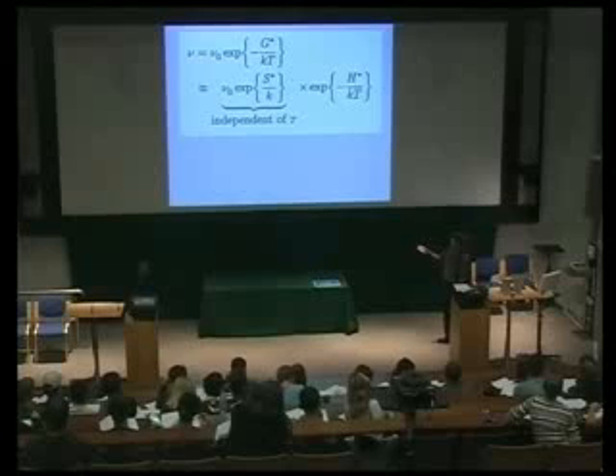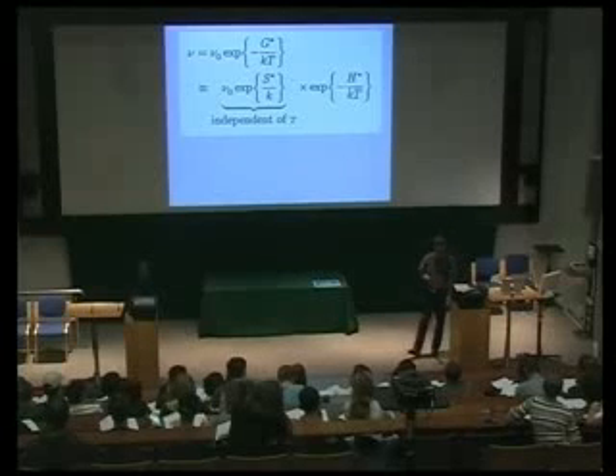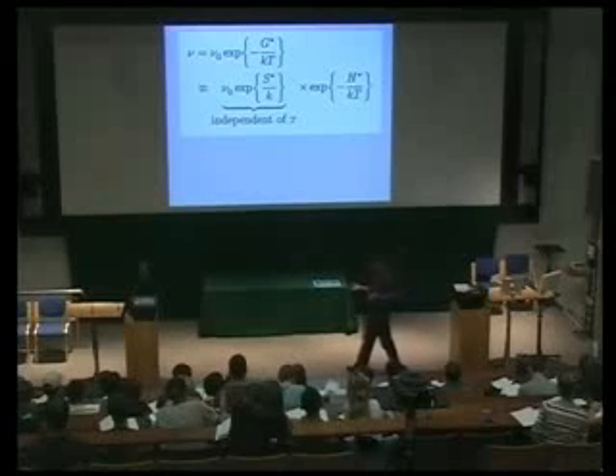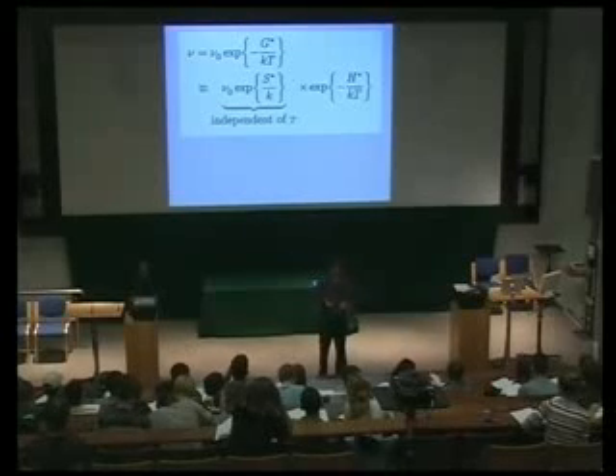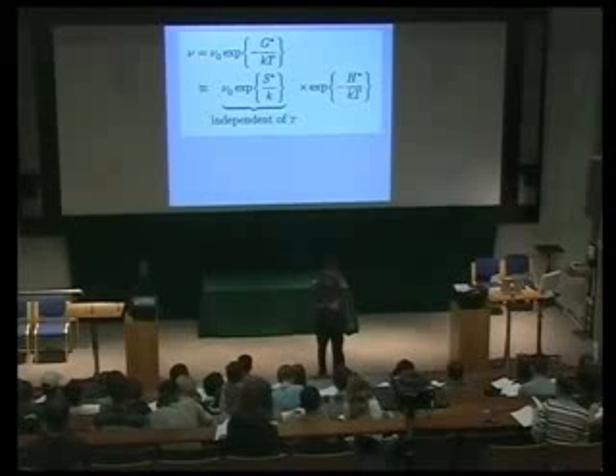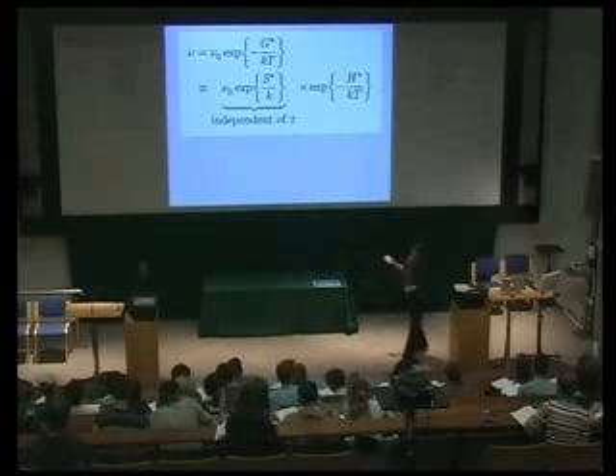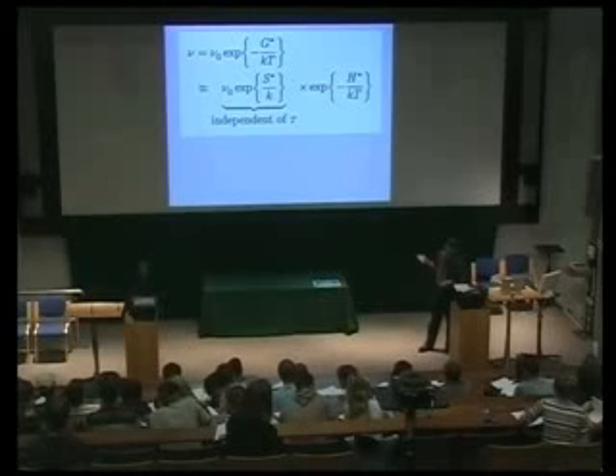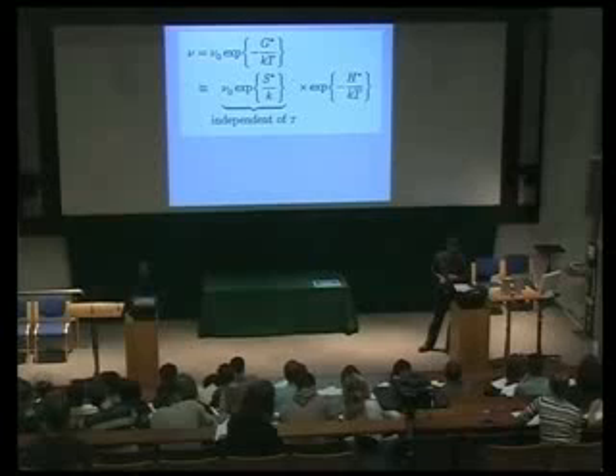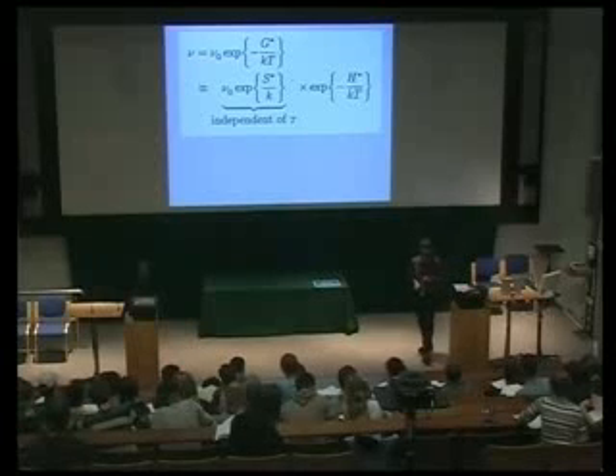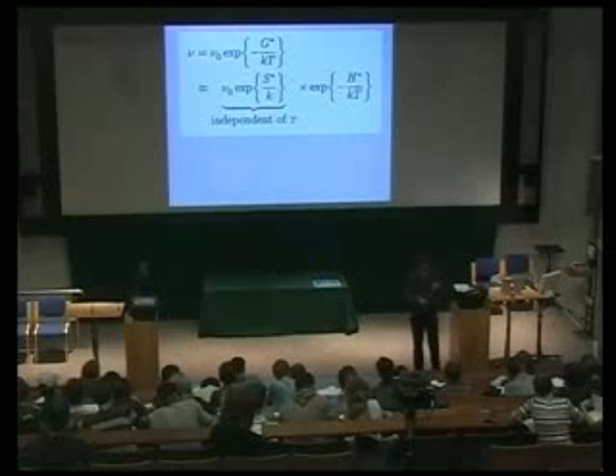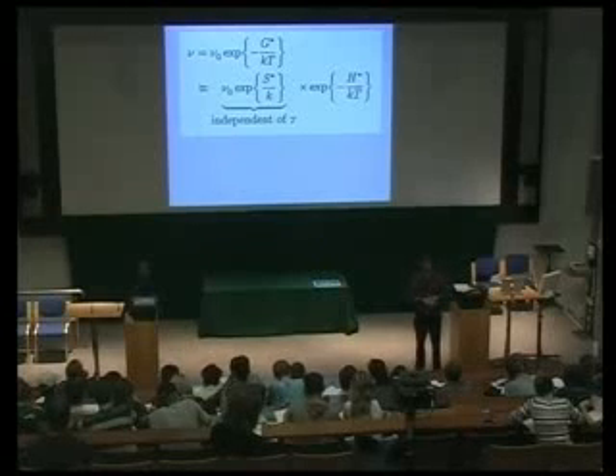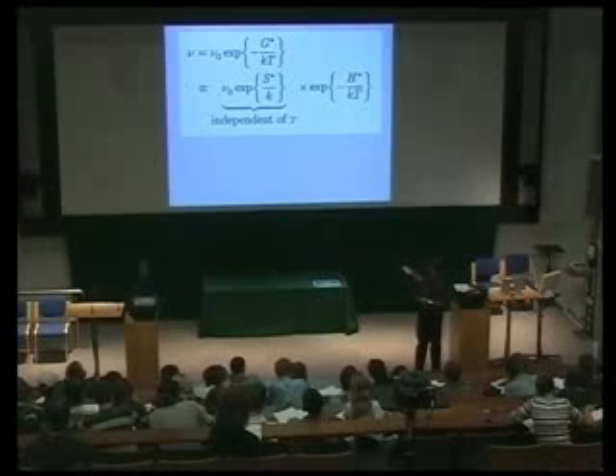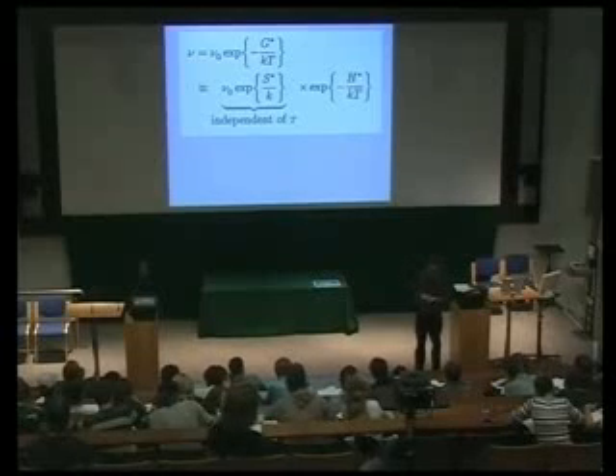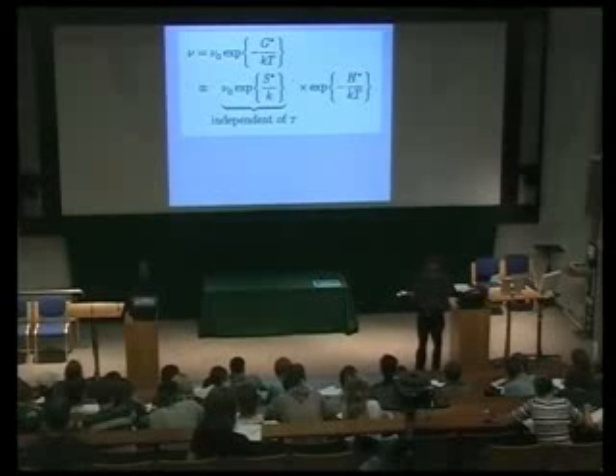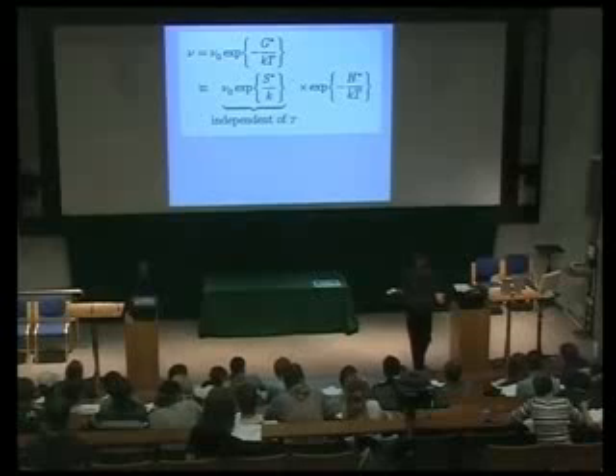And we've got to take that into account. So this is the attempt frequency, nu naught. In a crystalline solid, you could equate that to the Debye frequency, which is the vibration frequency of atoms. This is the probability of that jump being successful. So G star is the height of that activation barrier. It's the free energy, the activation free energy for that barrier. So if I multiply the probability of a successful jump by an attempt frequency, I get the real jump frequency. So this is just a normal Arrhenius equation. You happy with that?